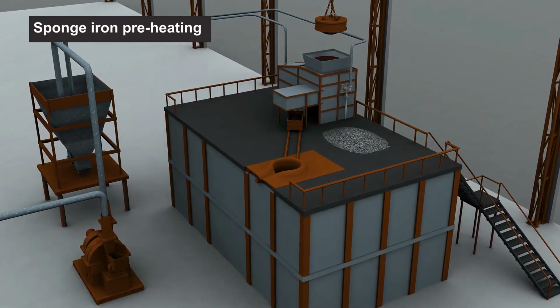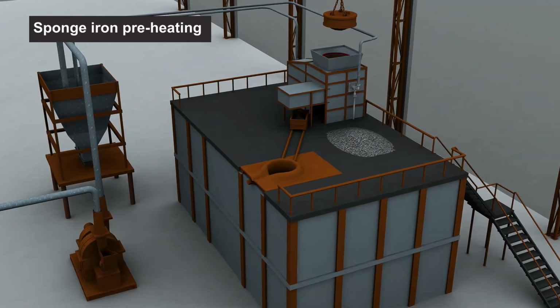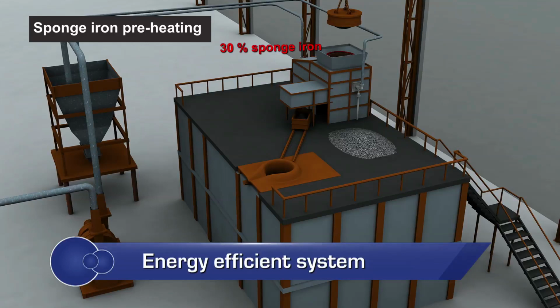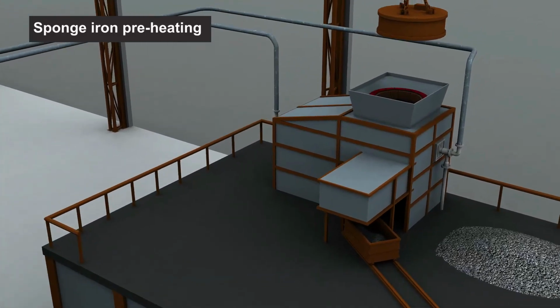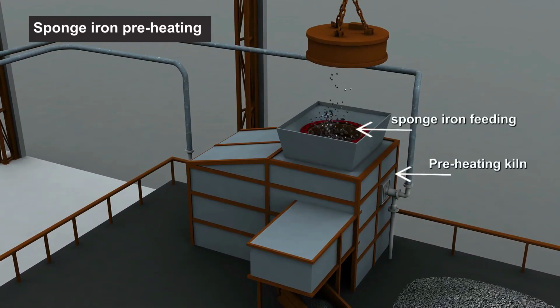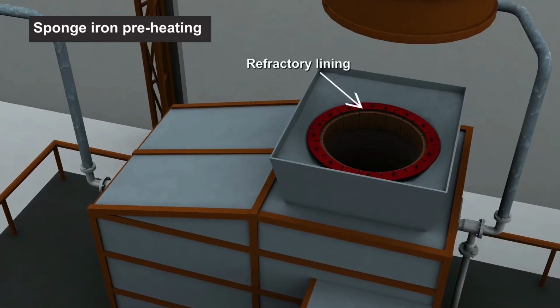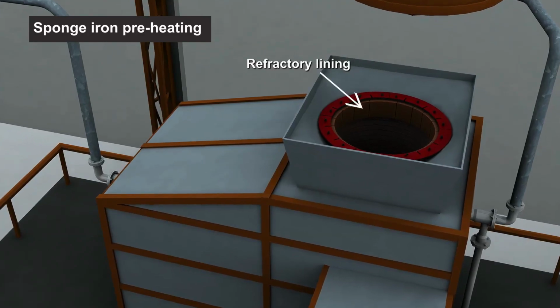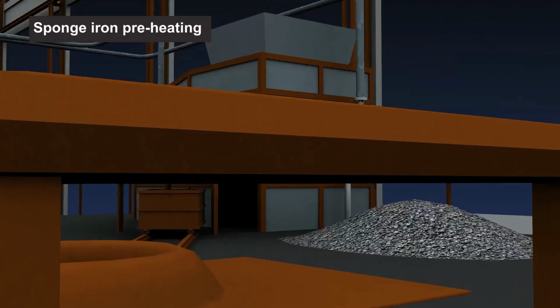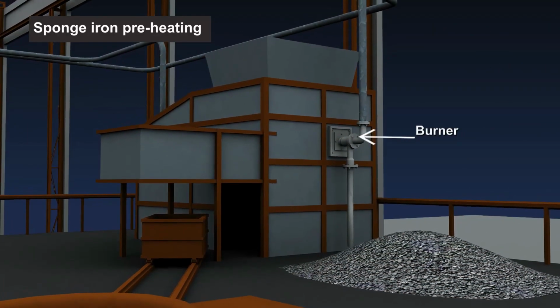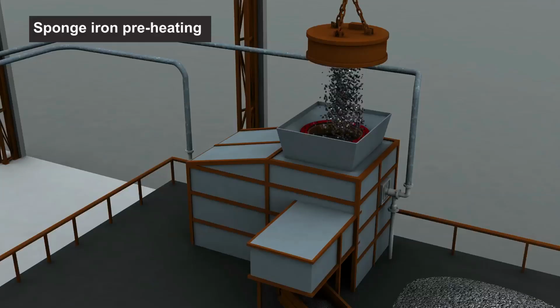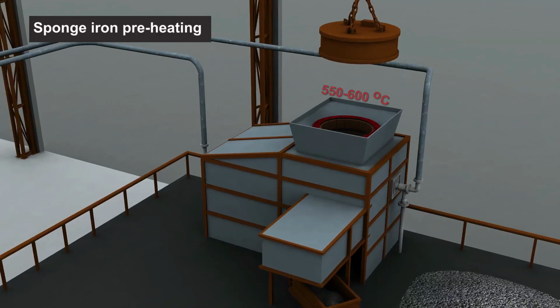To understand the system, let us consider a unit using a raw material mix of 30% sponge iron and 70% scrap. The process starts with feeding of sponge iron into the preheating kiln. The kiln is specially designed with refractory lining and burner blocks. These provide a controlled atmosphere to avoid overheating of the charge. The kiln is equipped to heat the sponge iron charge to a maximum of 550 to 600 degrees Celsius.